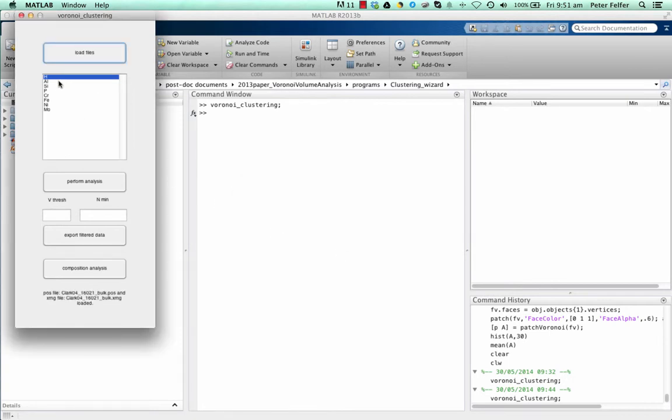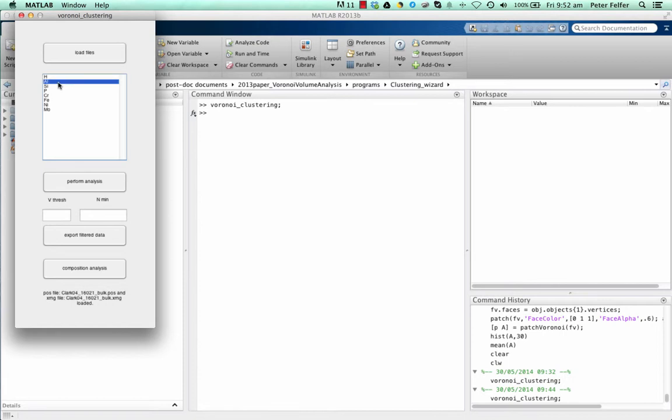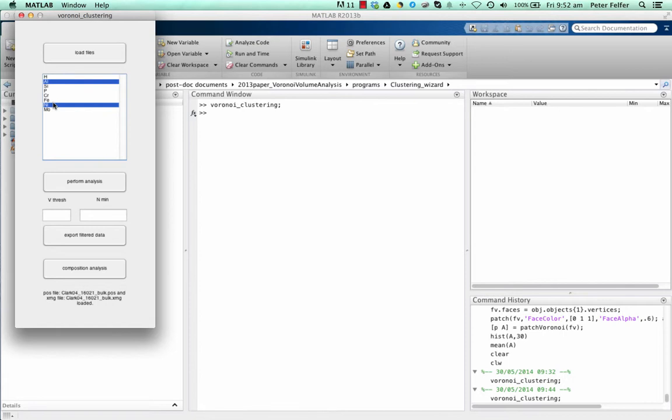Open that, and it will come up with the individual elements. Here you've got a list of the individual elements, and you can choose which ones you want to test for clustering. It's not limited to just testing for one element. You can actually combine elements by just command-clicking on a second element. In this system that I'm looking at, there's aluminum and nickel precipitates that form in the long run. If you want to look for clustering, you will look for clustering of aluminum and nickel together. That's pretty much it. Next thing is just click perform analysis, and the programs will do the rest for you.